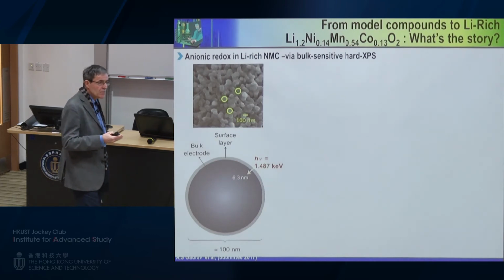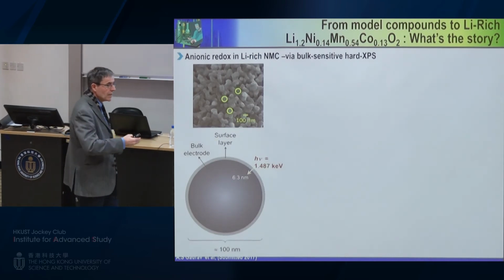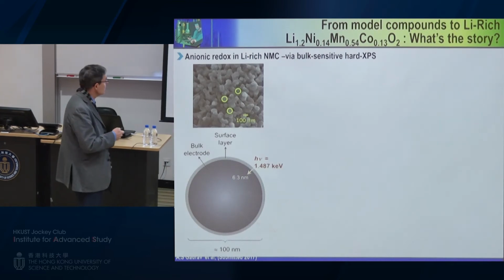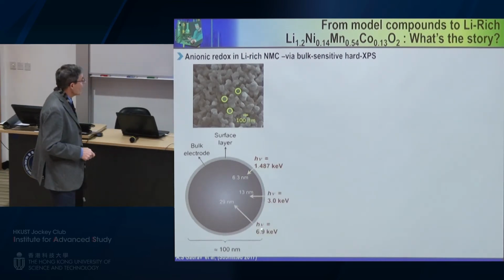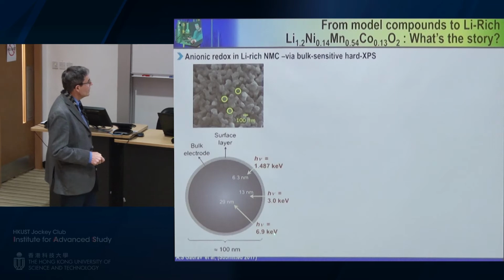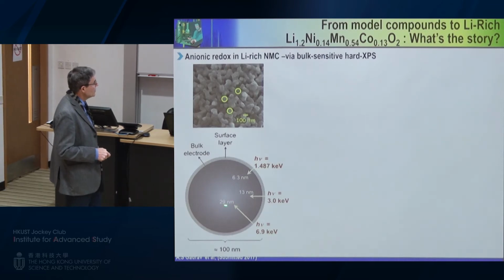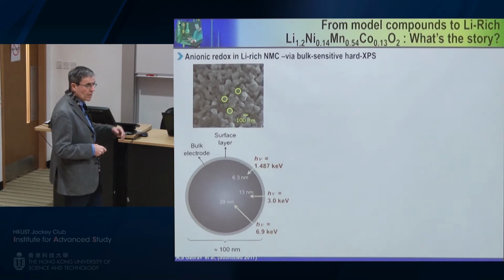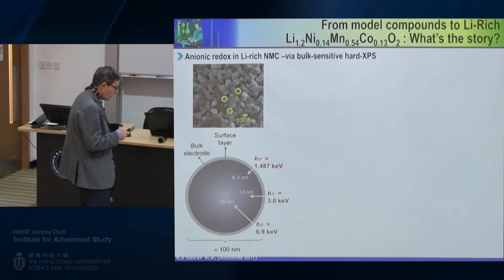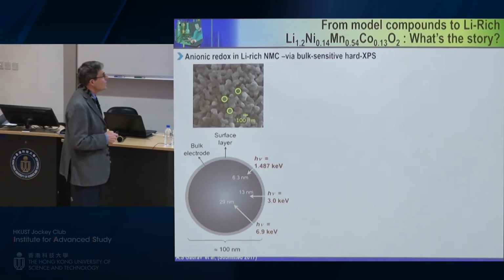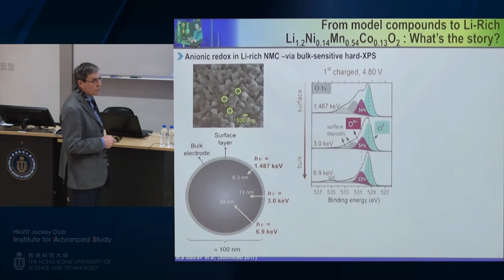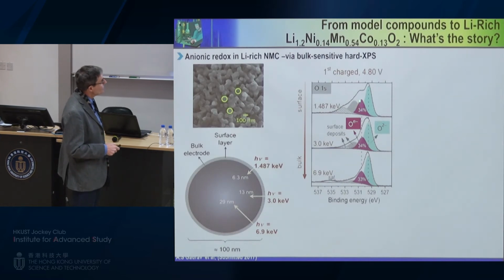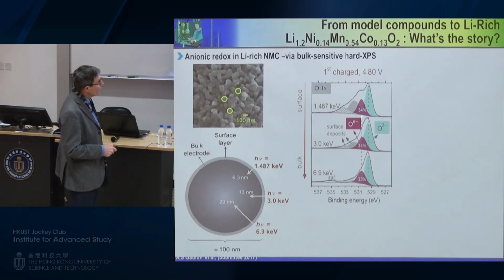By increasing intensity, we are really going to probe deeper and deeper into the particles. And we can go with 6.9 keV to about 20 nanometers, which means that there we sense the bulk of the particles. Now if we look at our XPS spectra, remember what I showed you before, you can see here the peak associated with the peroxo-like species, which is present.